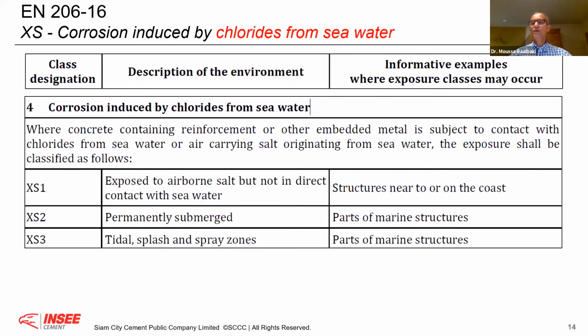Therefore, all the buildings, all the concrete that is built in the area of Colombo need to consider a minimum exposure condition of XS1. That is important. The second one is when the concrete is part of a structure that is either permanently submerged or in the tidal zone. It can be a bridge, for example. If it is permanently submerged, you take the XS2. And if it is in the tidal zone or spray zone, you take the XS3. Therefore, you see, it's not only about chloride from seawater. It depends where your element is.